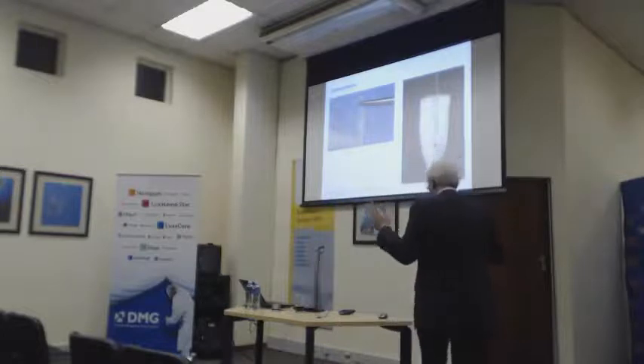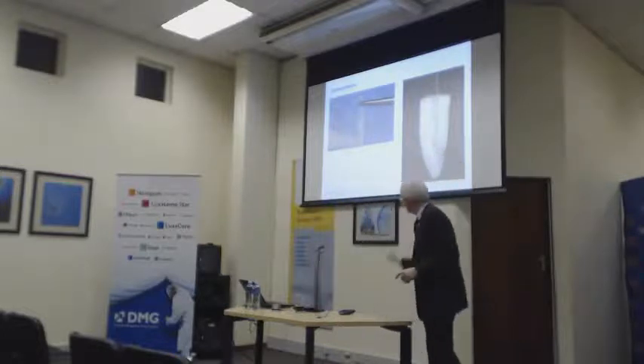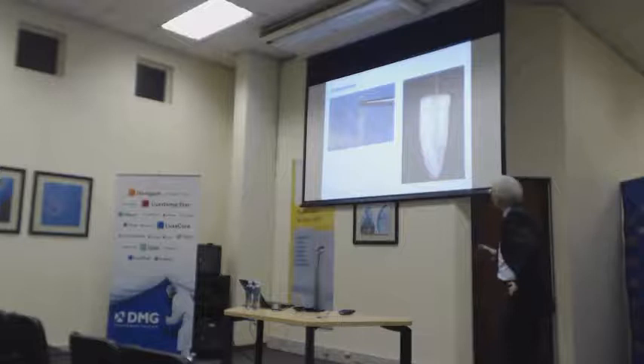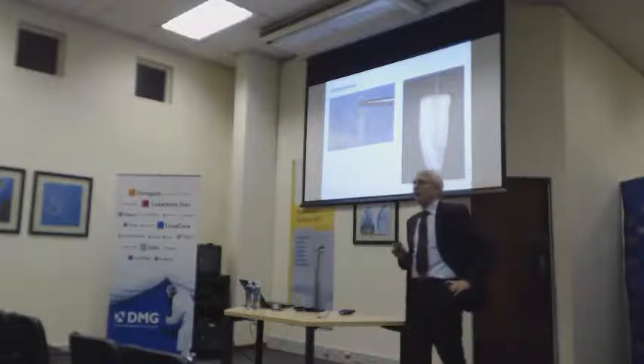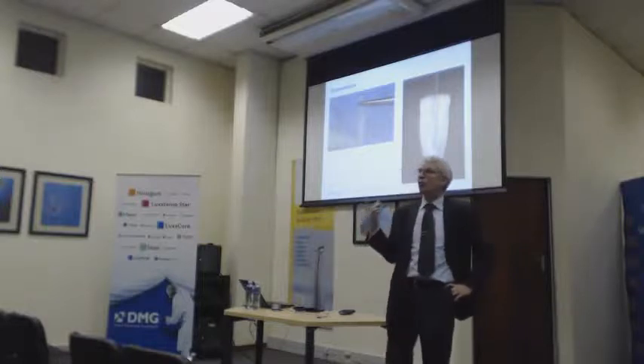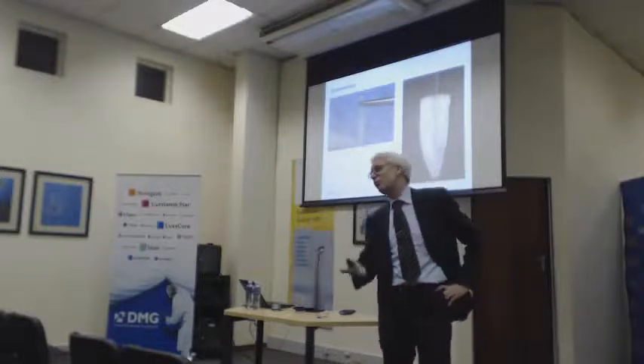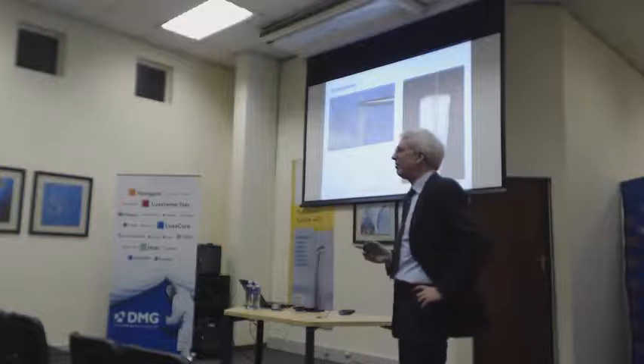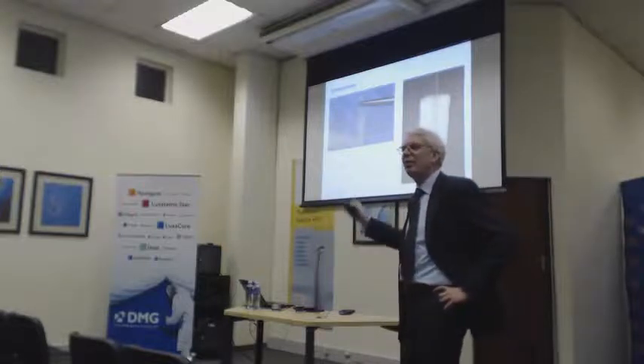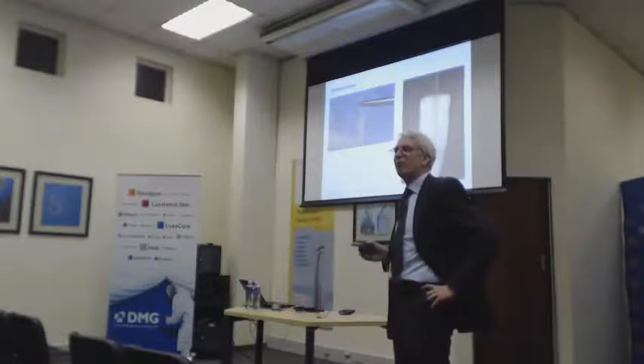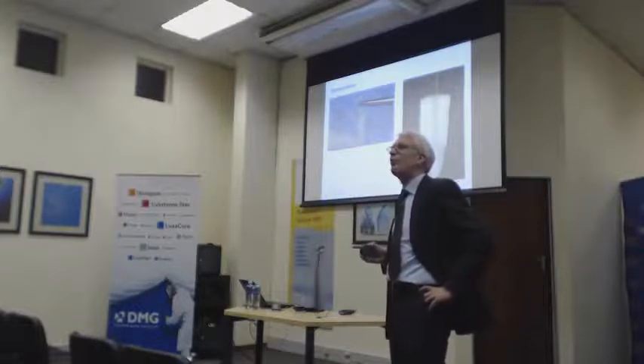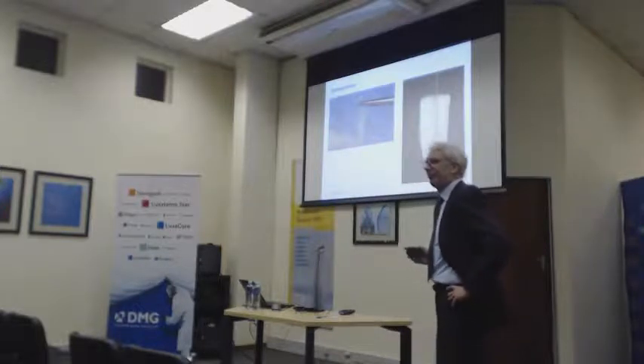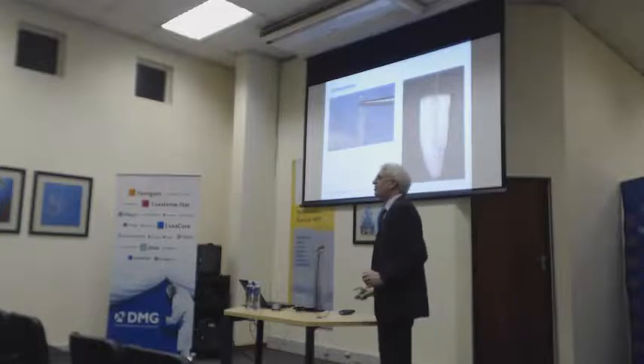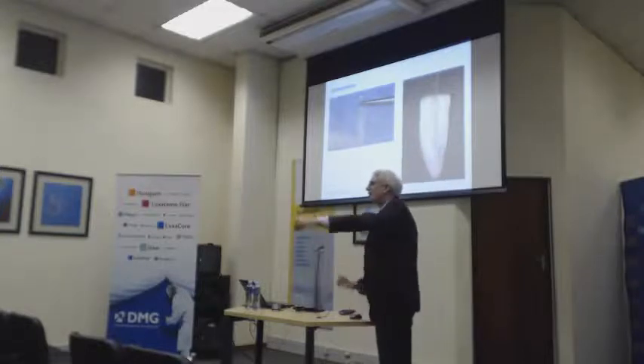And this is what you see with all of the products that are used in the root canal and work fine. So they're shortening your working time, and it's considerable. With Luxacore, you have a normal working time of 1 minute 45, so plenty. You can do anything you like. But if you're using it with the Luxapost, you have a working time of 20 seconds. Okay, I can see a little bit of concern in some of the faces.